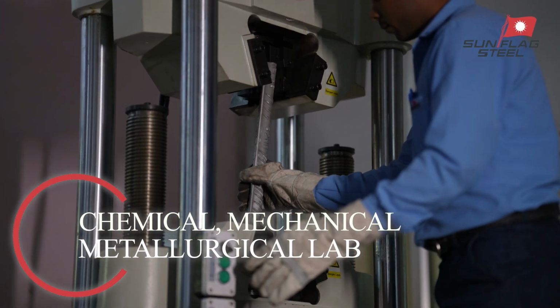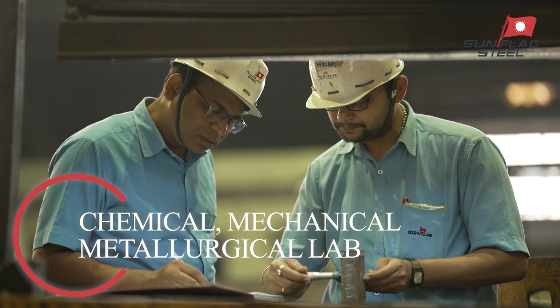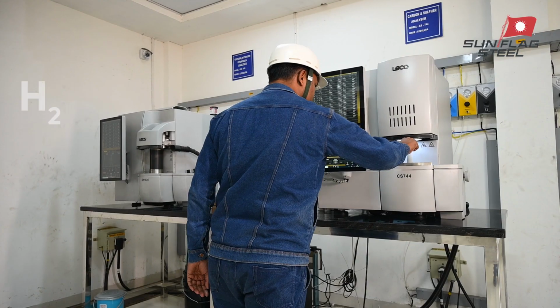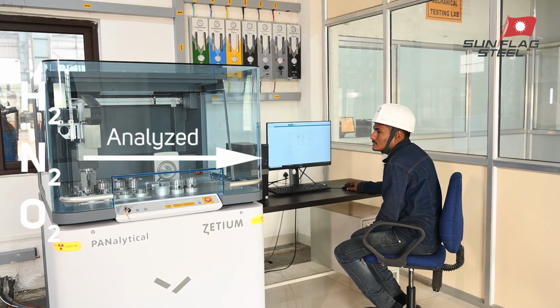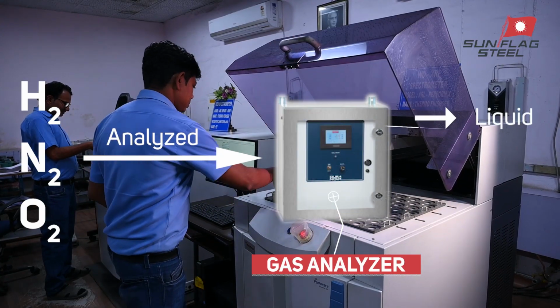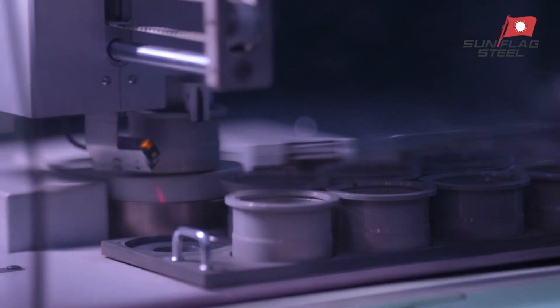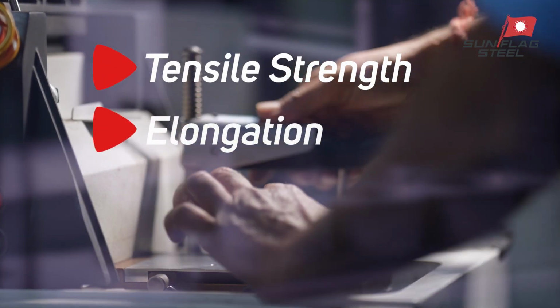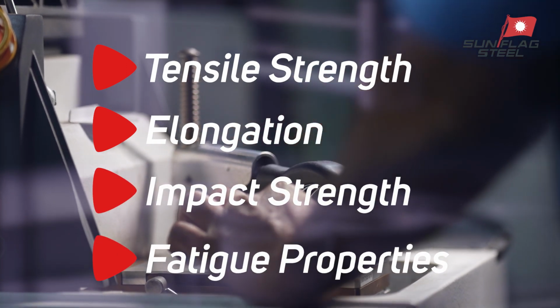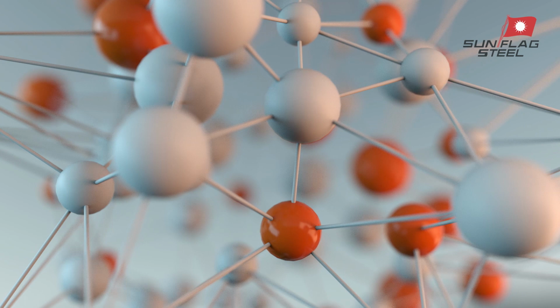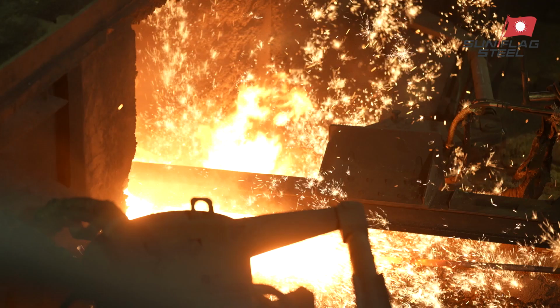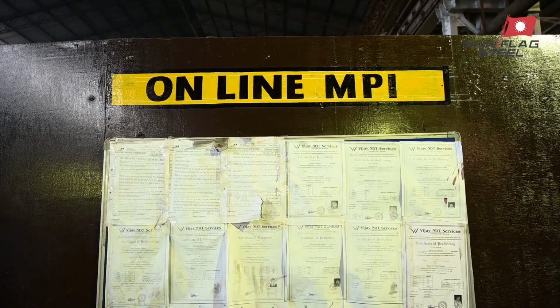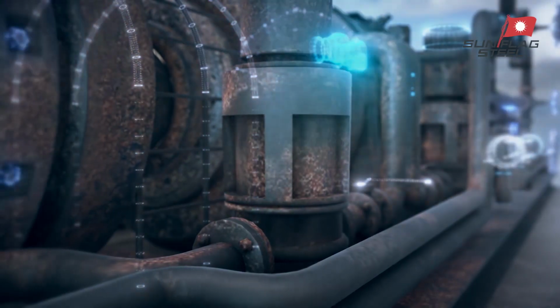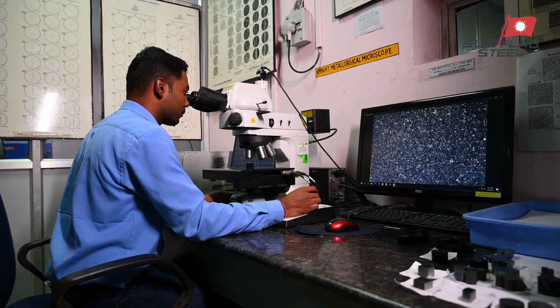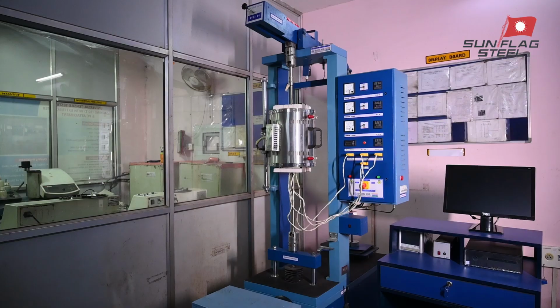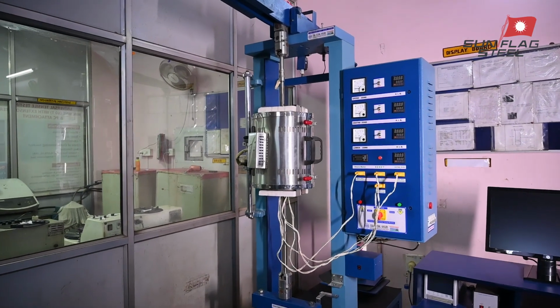Chemical, mechanical and metallurgical lab. Chemical composition is tested during the process by spectrometer. Gases like hydrogen, nitrogen and oxygen are analyzed by gas analyzer at liquid and solid stage. Latest version testing equipment analyzes mechanical properties like tensile strength, elongation, impact strength, fatigue properties. Microstructure, so important to mechanical properties, and response to heat treatment is associated and recorded on image analyzer. For assessment and analysis of surface properties, scanning electron microscope is used. For detailed inclusion analysis, immersion ultrasonic testing is used.